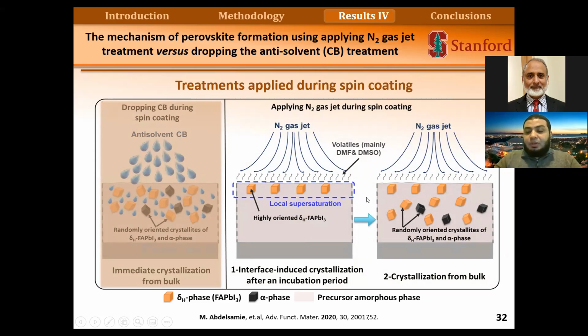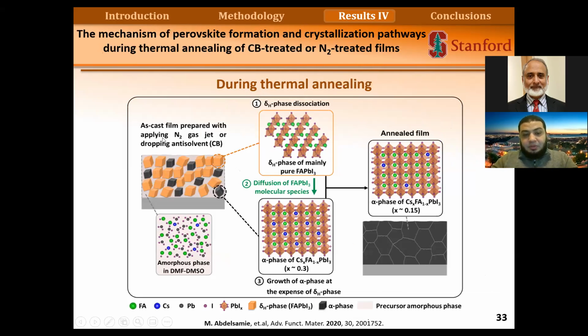And as we increase the nitrogen drying time, then we get supersaturation in the bulk. So we initially have a local supersaturation on the top surface, and then we have saturation in the bulk, and we get some randomly oriented crystals in the bulk. So we have two steps happening during this process. And in both cases, after we form the film, we end up with delta phase and alpha phase, and also some amorphous phase. So this is the picture of what's happening during film formation. This is the as-cast film. After we spin coat the film, we get some delta phase and some alpha phase, and also some amorphous material. But we need to reach the final product on the right, which is the black phase.